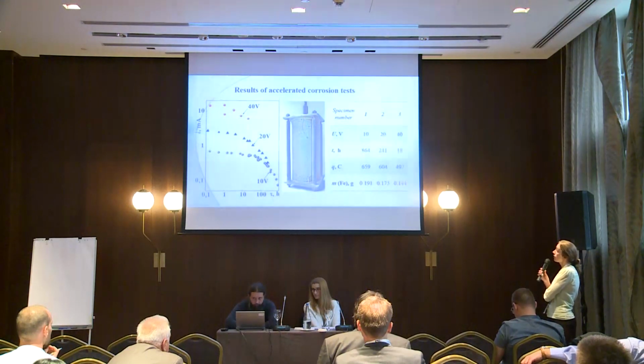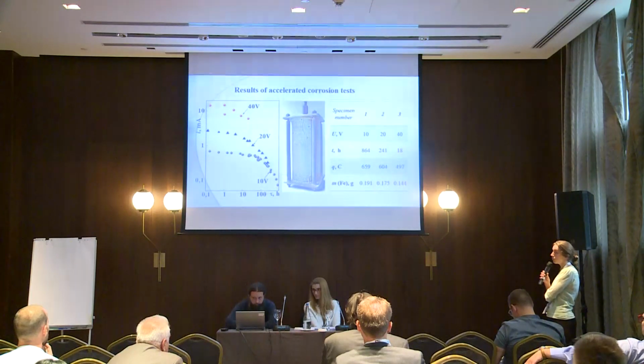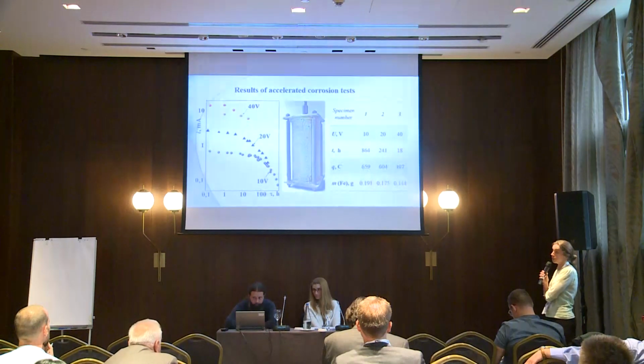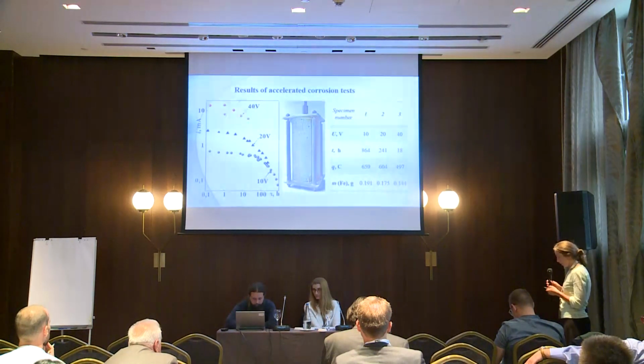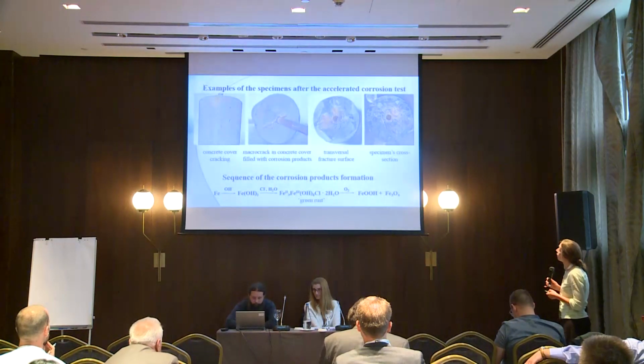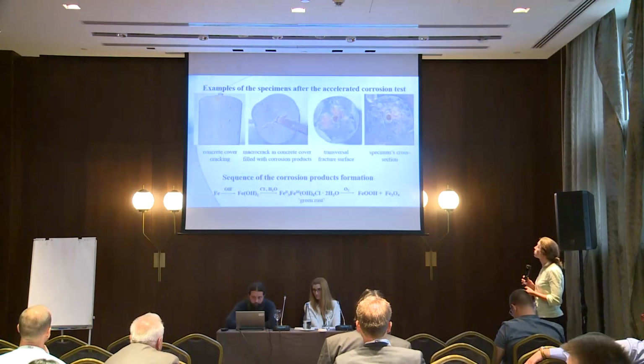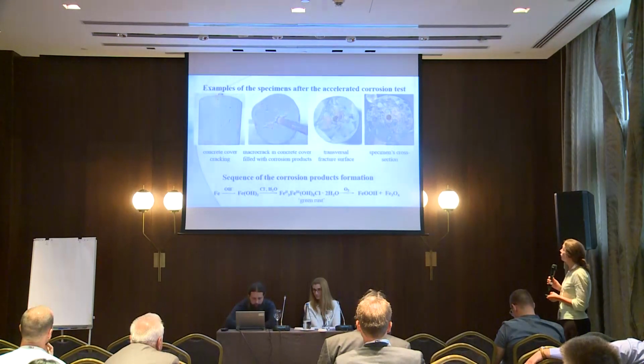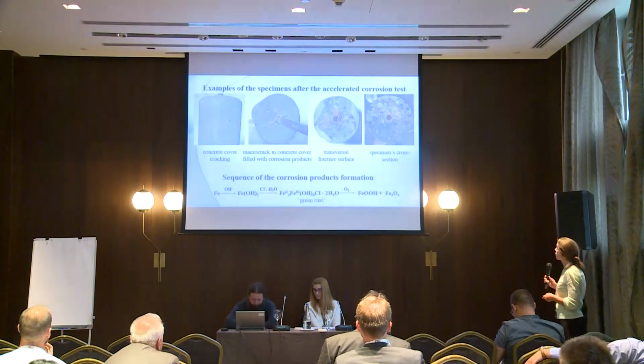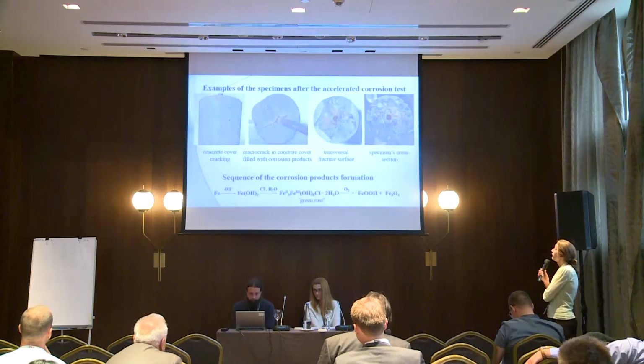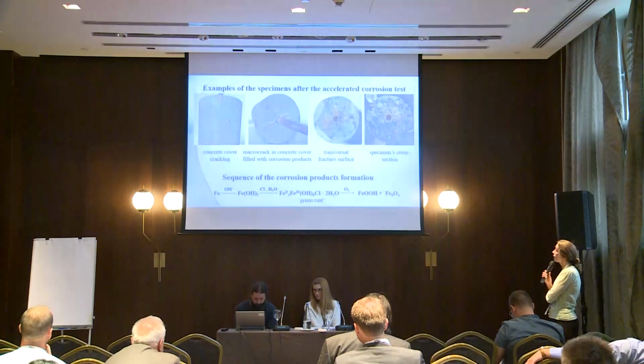We concluded that under moderate polarization, more adequate results of simulation should be achieved. Here is an example of a broken specimen after our experiments, and an interesting peculiarity was revealed.